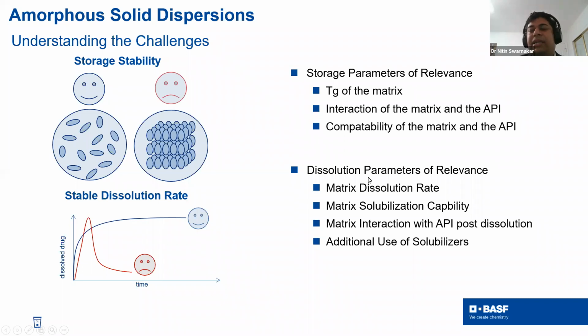Now dissolution parameter, I think maybe I'll not go into detail on this, but simply, take matrix dissolution rate. If your matrix is hydrophilic in nature, then immediately it will dissolve. Sometimes what happens is that your drug will release faster. And in this case, in the GIT, what we want is that the precipitation rate must not be higher than the absorption rate for the drug molecule. This is pretty much what we generally see. So if your absorption rate is faster than the precipitation rate, then it's better.